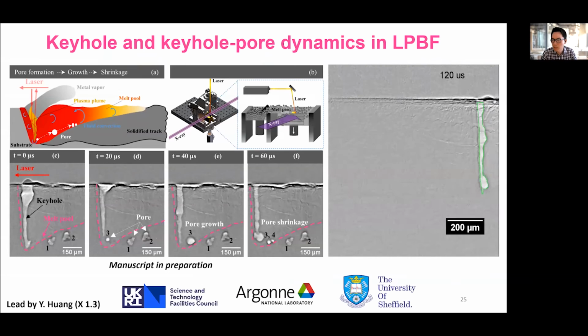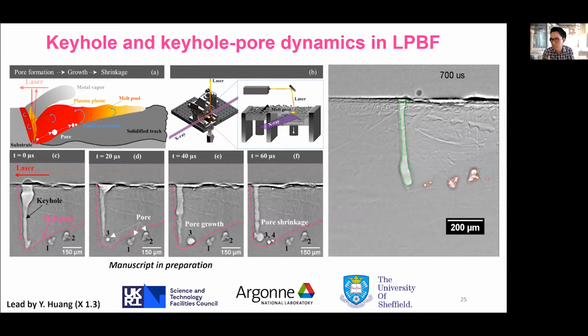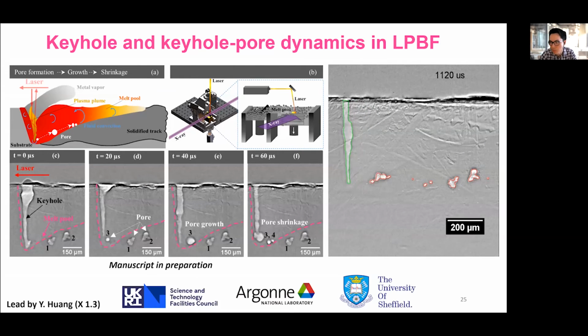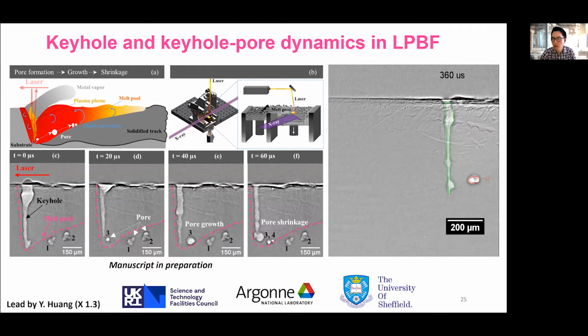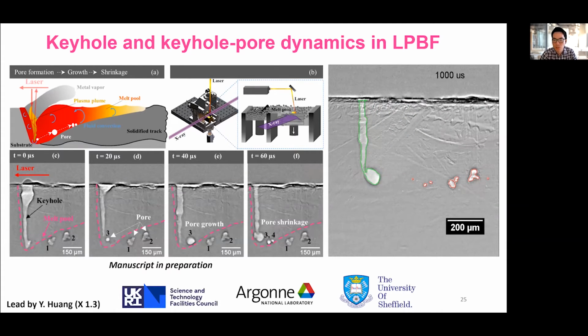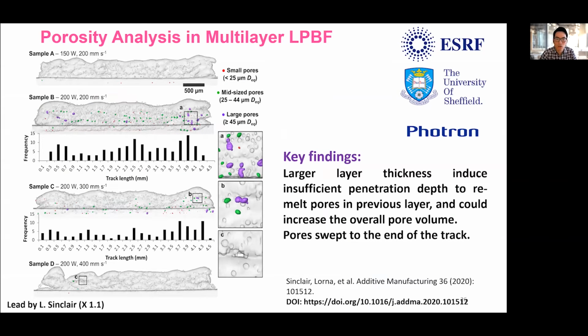So there are many other things you can do. You can actually look at the morphology of the laser generated cavity during the process. You can also see how voids are forming, highlighted in red on the far right. And we have a team of researchers studying how these bubbles form, trying to come up with ways to mitigate that. We also have students looking at what happens when you're spreading this layer of powder within the machine and you change different parameters. How does that actually influence the imperfection formation? As you can see on the top left corner, increasing the power under the condition studied dramatically influenced the imperfection formation, and these voids could cause some troubles further down the line.